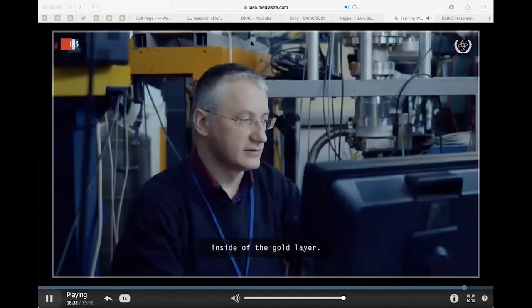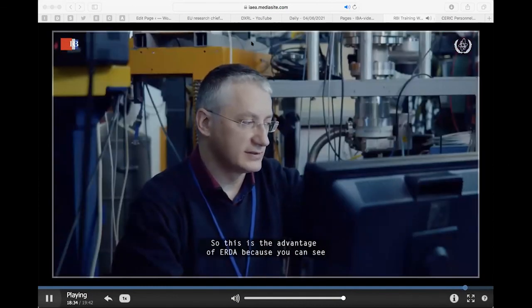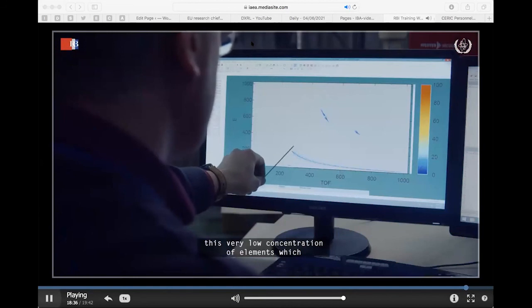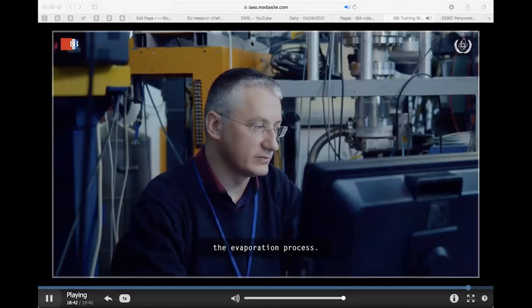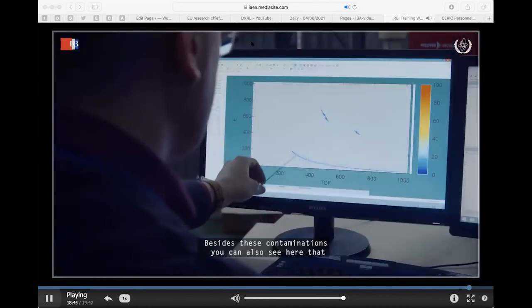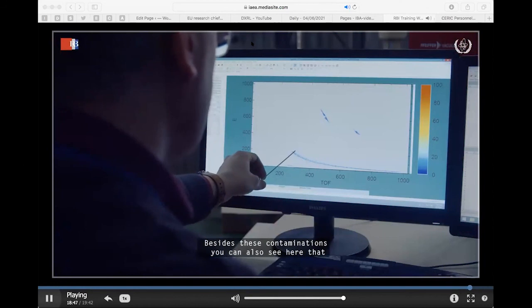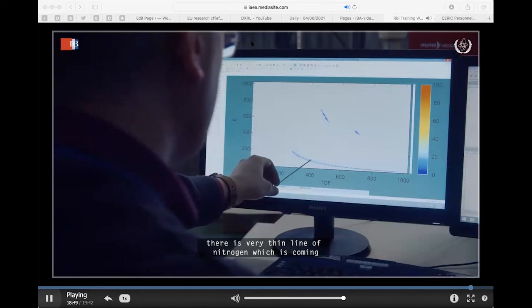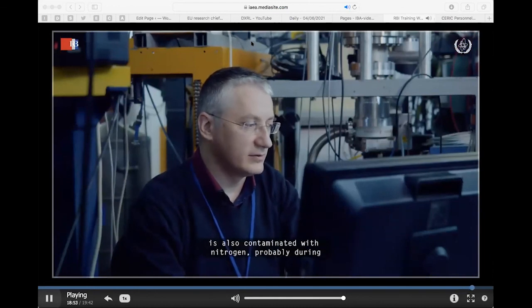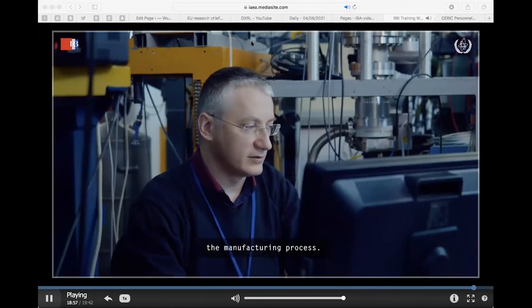gold layer. So this is the advantage of ERD, because you can see these very low concentrations of elements, which are actually contaminations introduced during the evaporation process. Besides these contaminations, you can also see here that there is a very thin line of nitrogen, which is coming from the carbon backing, which means that the carbon is also contaminated with nitrogen, probably during the manufacturing process.